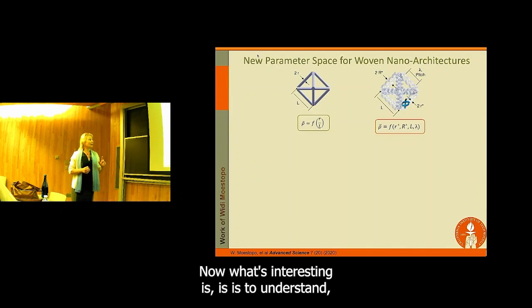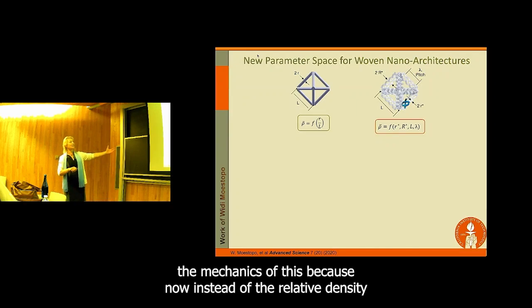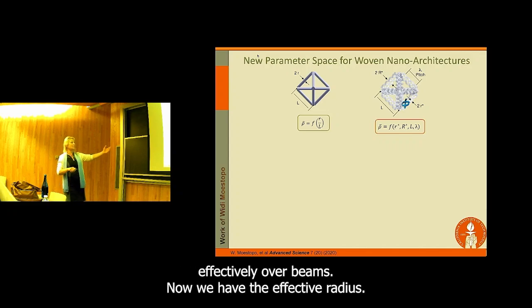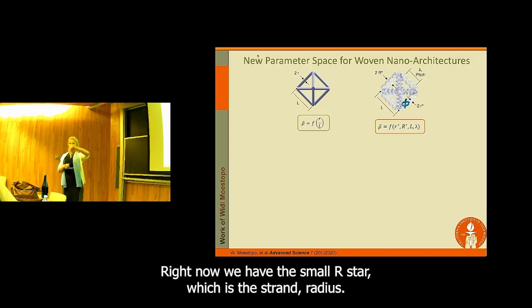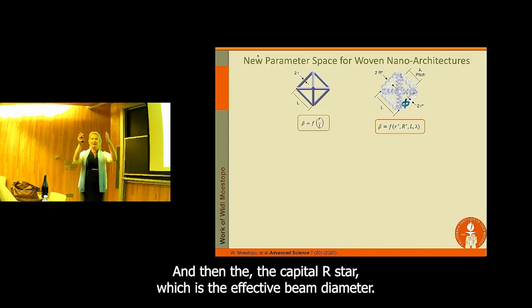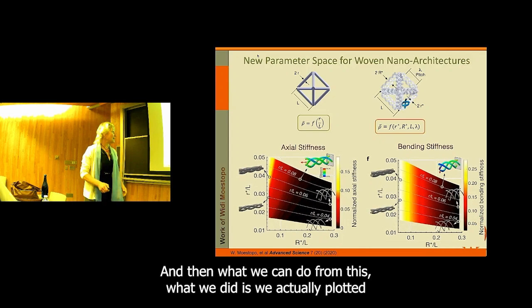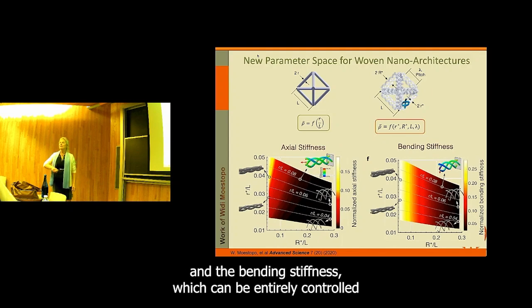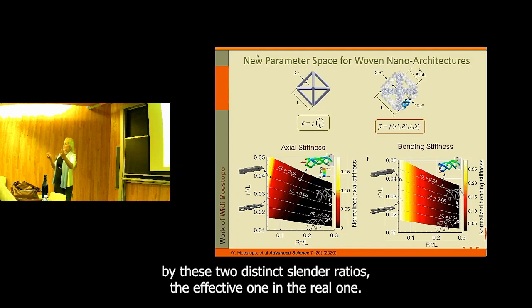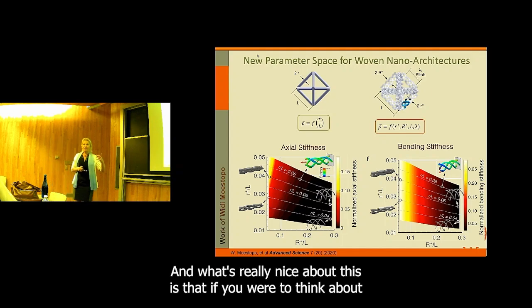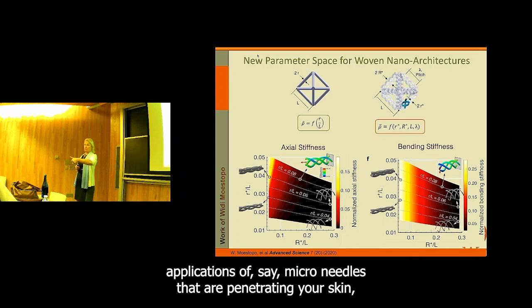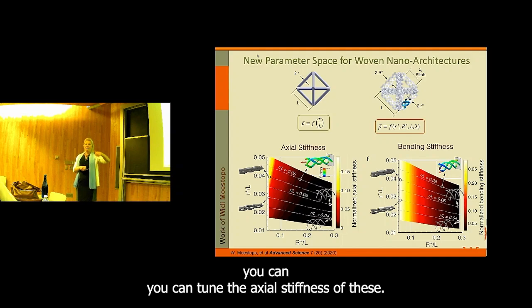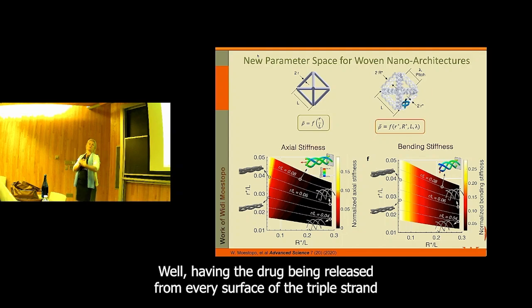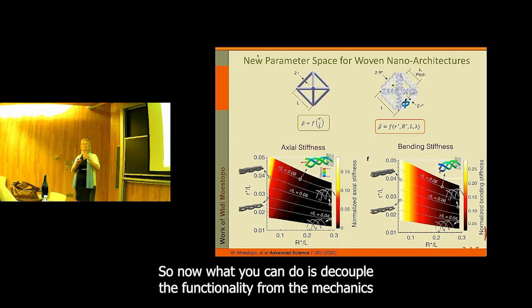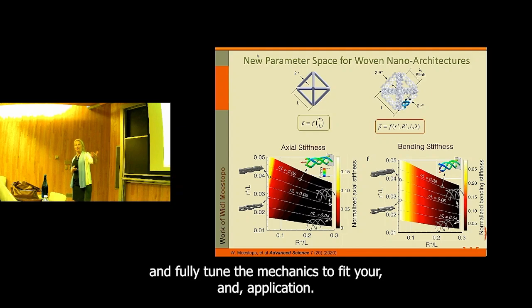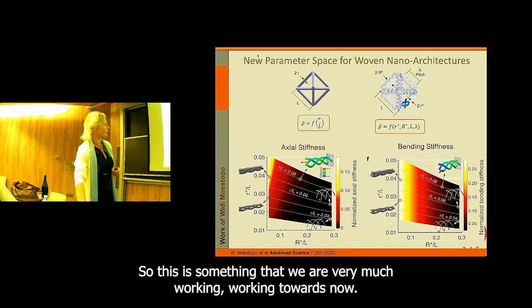Now, what's interesting is to understand the mechanics of this, because instead of the relative density being a very simple function of the slenderness ratio of your beams, now we have the effective radius. We have the small r star, which is the strand radius, and the capital R star, which is the effective beam diameter. What Widi did is he plotted the entire parameter space of the axial stiffness and the bending stiffness, which can be entirely controlled by these 2 distinct slenderness ratios, the effective one and the real one. What's really nice is that if you think about applications such as microneedles penetrating your skin, for example for drug delivery or patches, you can tune the axial stiffness while having the drug released from every surface of the triple strand. So now you can decouple the functionality from the mechanics and fully tune the mechanics to fit your end application. This is something we are very much working towards now.